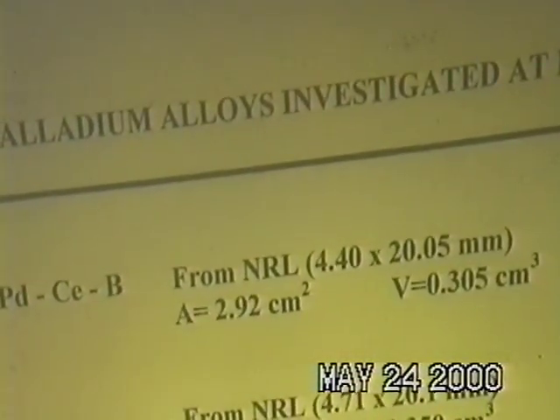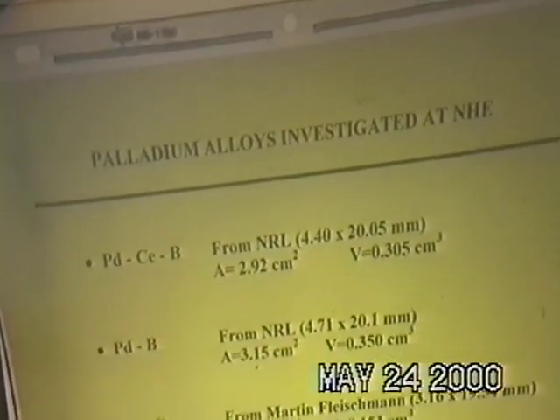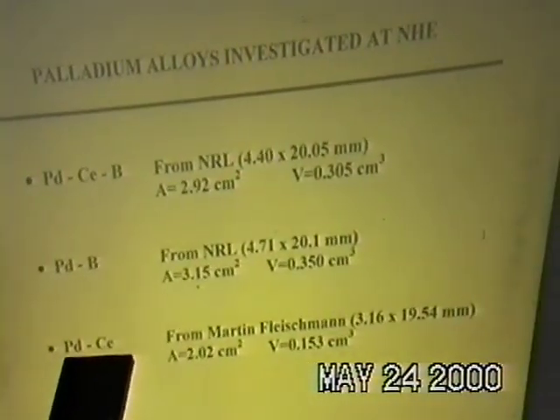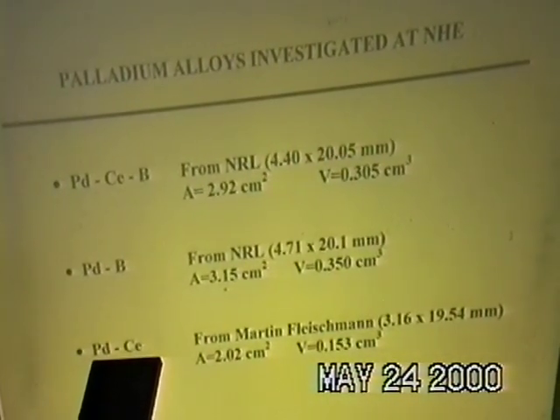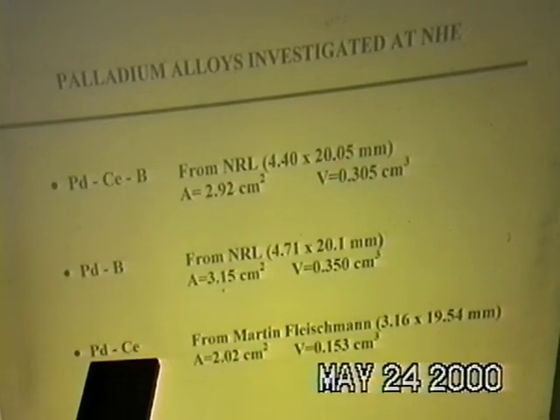The 3 studies I will talk about today, the palladium cerium boron made by NRL. This is 4.4 by 20.05 millimeters, area and volume shown there. The palladium boron, which had been very successful in China Lake in producing excess heat. I had 7 out of 8 produce excess heat prior to Japan. And this one also produced excess heat, as we'll see, in Japan as well. The palladium cerium was given to me by Martin Fleischmann a few years earlier and produced excess heat in China Lake. And I took it to Japan and produced excess heat also there.